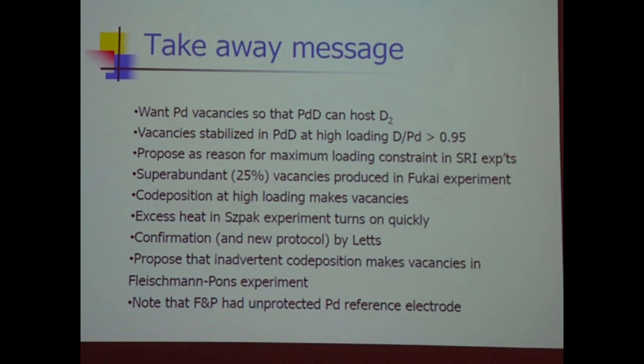Is D2 or D in certain condition when D2 goes into palladium? Well, when D2 goes into palladium, in bulk palladium, the D2 breaks up into individual deuterium atoms, and they go to the octahedral sites. Yes. Now, here we're arguing that we make vacancies on the surface by co-depositing at high current density. And near the vacancy, there's low electron density. So there we can make something that looks like a D2. It's not quite D2. The separation is more than for the vacuum molecule. But from my perspective, it's D2 under conditions of reasonably high electron density, so it can be screening. Yeah, we're going to be very interested in that shortly. Okay.